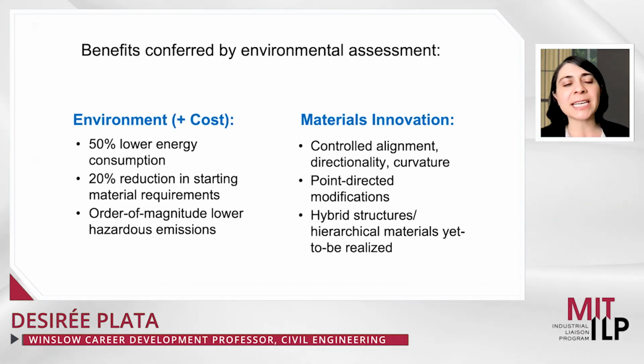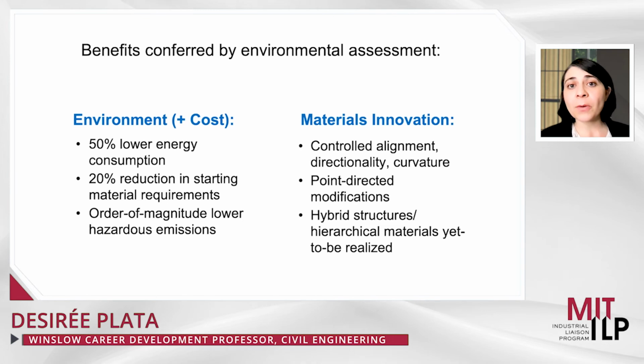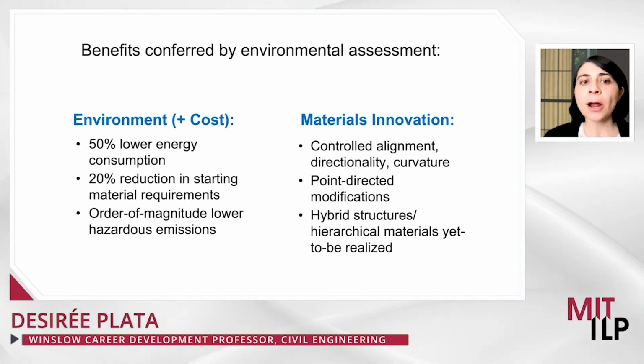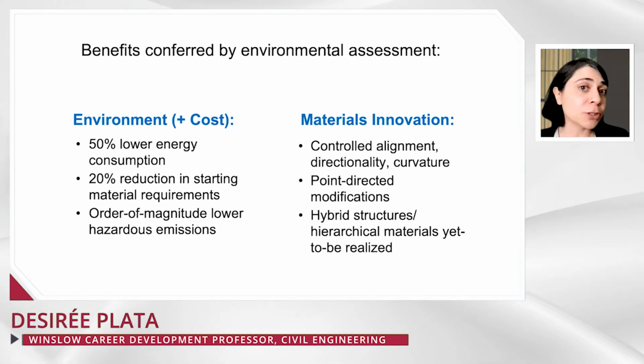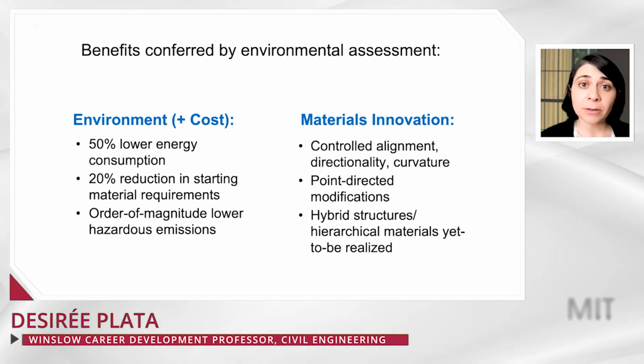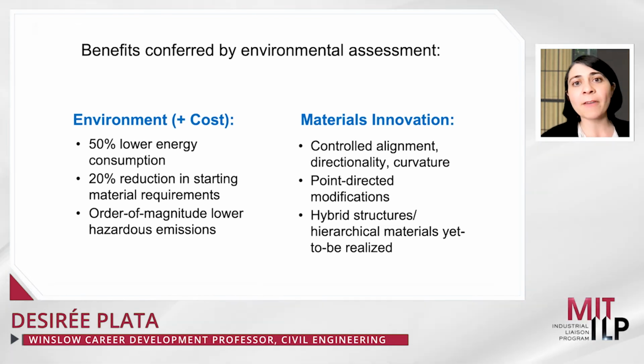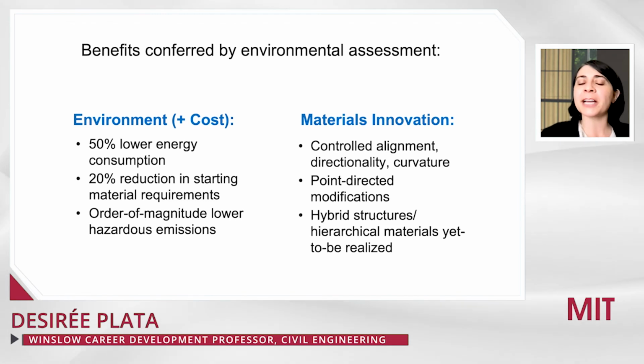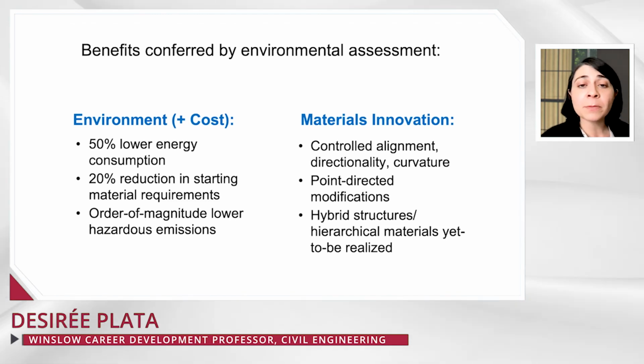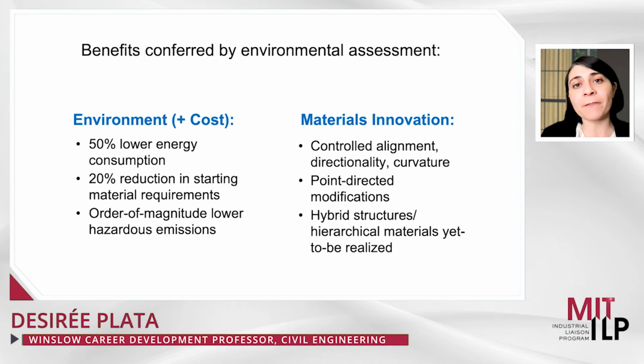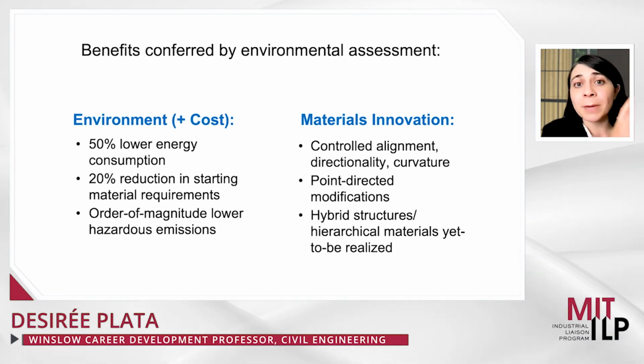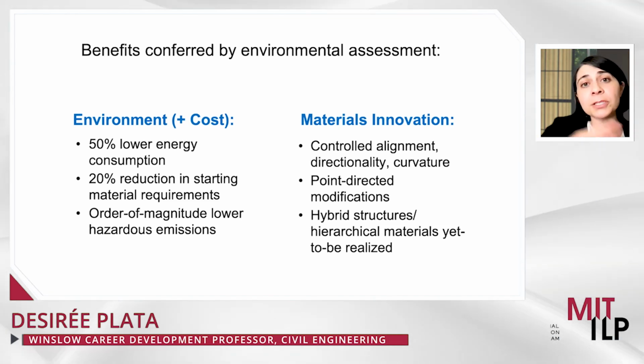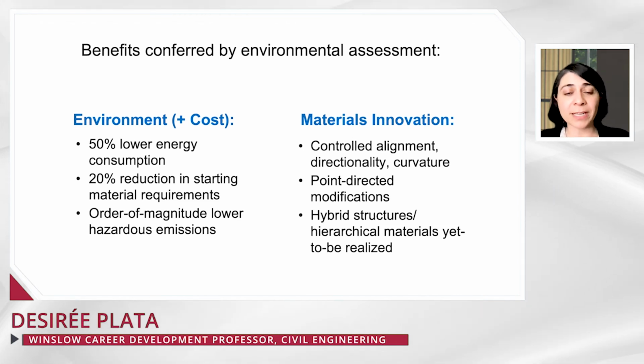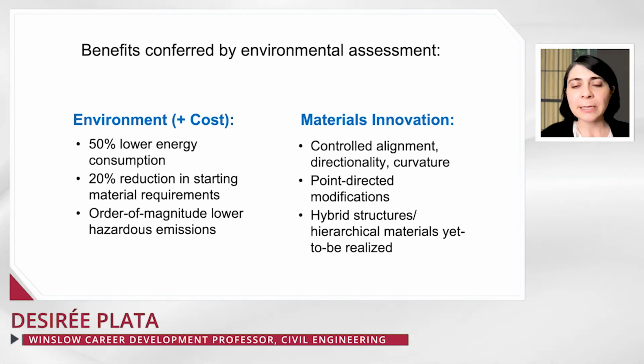We're also able to see that we have a 50% lower energy consumption using this alkyne-assisted carbon nanotube growth. We are able to reduce the starting material requirements by an order of magnitude or more. And we have many orders of magnitude lower hazardous emissions. So those VOCs and polycyclic aromatic hydrocarbons that I showed you earlier can be nearly eliminated in the effluent stream. And so this gives you much better control over your process and also provides great environmental benefits. So you don't have to worry about your neighbors, the planet, or ecological systems that would be impacted.